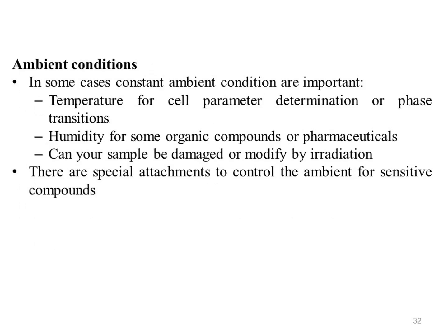What are the ambient conditions? In some cases, constant ambient conditions are important. Temperature for cell parameter determination or phase transitions. Humidity for some organic compounds or pharmaceuticals. Can your sample be damaged or modified by irradiation? Normally copper radiations are not too highly energetic. There are special attachments to control the ambient for sensitive compounds.